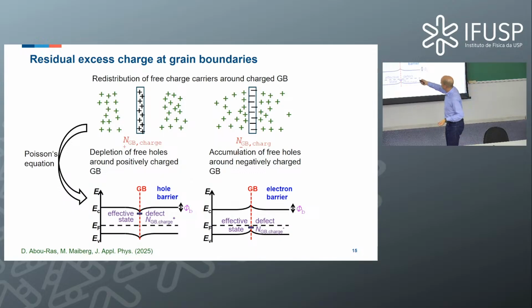This means we have localized charges here. Now, if we look at a semiconductor, we know that there are free charge carriers, free electrons and free holes. And what do they do? They will redistribute. If you take a p-type semiconductor, we have an excess in holes. And the holes, of course, if you have a positively charged grain boundary, they would be repelled by the grain boundary. So there would be a depletion of free holes around the grain boundary, right? And correspondingly, if you have a negatively charged grain boundary, where the excess charge is negative, then of course the holes would be attracted.